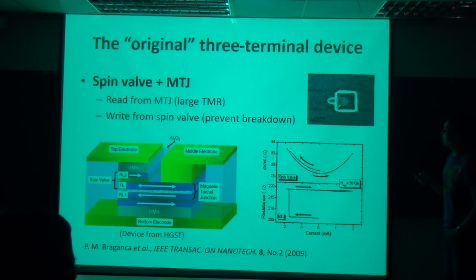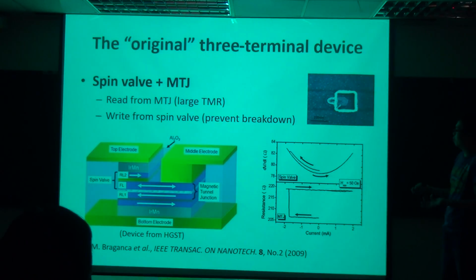Unfortunately, this was the best device I could get, and I never successfully put down top electrodes without them touching each other. The gap is only maybe 30 or 50 nanometers, and we just use school level tools, so it's very hard for us to get this type of structure. So this is the best I can get. You can see we have this spin valve part over here, and at the bottom we have this tunnel junction.